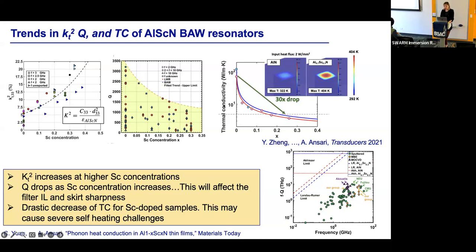Another thing that we measured was the thermal conductivity of scandium aluminum nitride, and we realized that as the scandium is increasing, there's a 30x drop in the thermal conductivity, which means that the self-heating becomes a lot more severe in aluminum scandium nitride FBARs, compared to aluminum nitride. Especially for 5G applications, we know that more and more power needs to be dumped into these resonators, and the temperature can go up a lot if we are using AlScN instead of aluminum nitride. So my group is interested in all these material properties of aluminum scandium nitride and the challenges that come with adding more and more bandwidth to your filter.